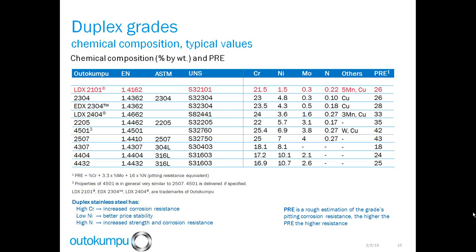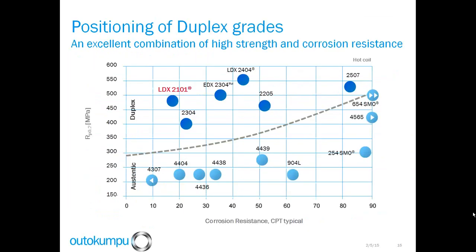Also shown is the PRE, or pitting resistance equivalent. This is shown in the table and can be used to rank the corrosion resistance of stainless steels. The PRE is calculated as the percent chrome plus 3.3 times percent molybdenum plus 16 times the nitrogen content. The higher chrome and nitrogen of the duplex stainless steels result in the high levels of corrosion resistance.